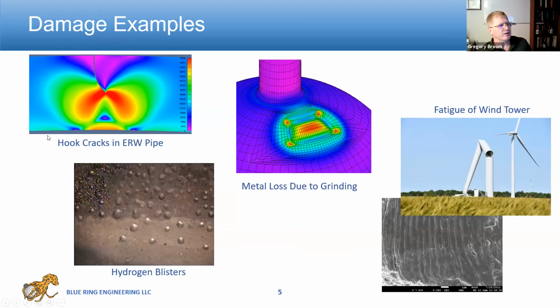So what you're looking at in the picture is a computer model to determine the stresses at the tip of that crack. So then we can determine, will that crack remain stable? How fast will that crack grow? And then, does that give us enough time to operate? When do we need to repair? When do we need to replace that equipment?